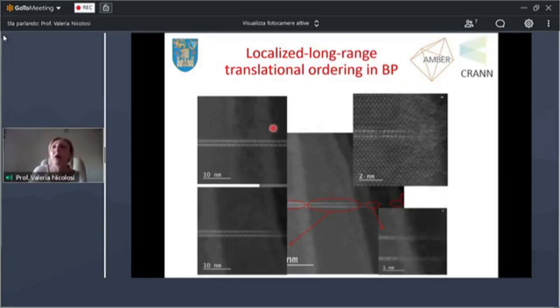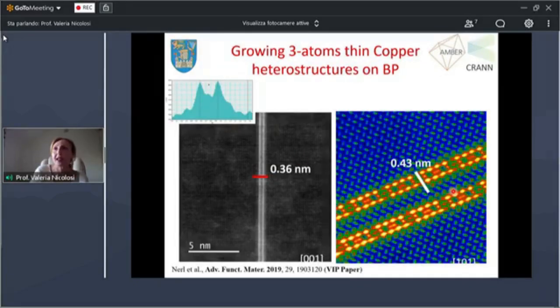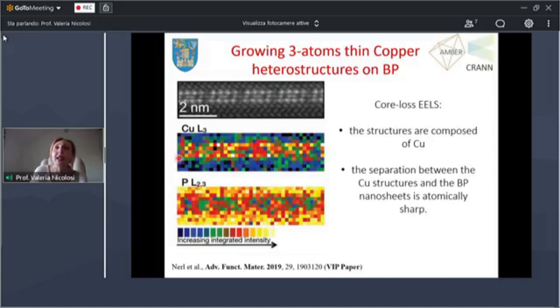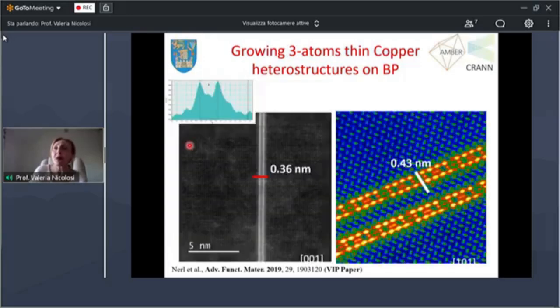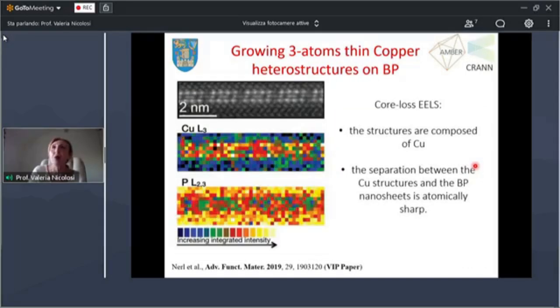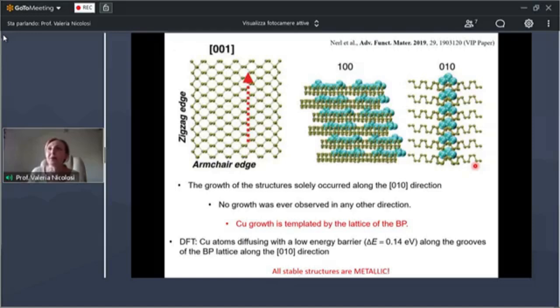These are wires that we can grow out of copper. In fact, we have verified that through EELS spectroscopy. So you actually can grow wires that are entirely made of copper, a metal, into a semiconducting material, and you don't have any presence of any oxide or anything like that. This is how these wires, for example, look under two different symmetry directions. So the beauty of really making a 3 atoms wide type of metallic nanowire onto a black phosphorus nanosheet really opens up a lot of possibility. Beautifully, we have tapped into our colleagues at Imperial College and Trinity College to do some DFT calculations, and they have indeed verified that these copper wires always grow around the 010 direction.